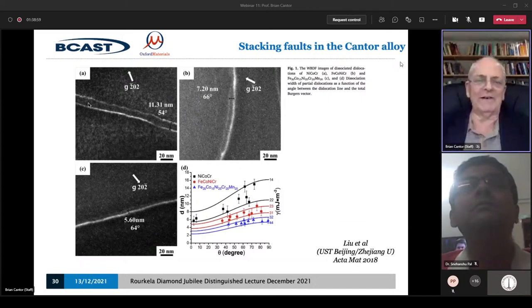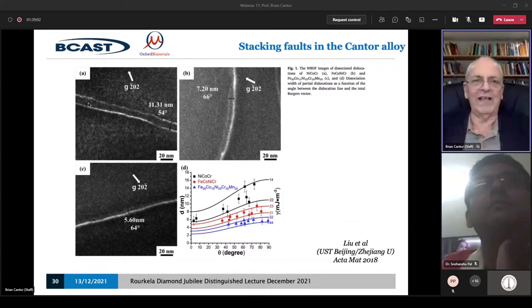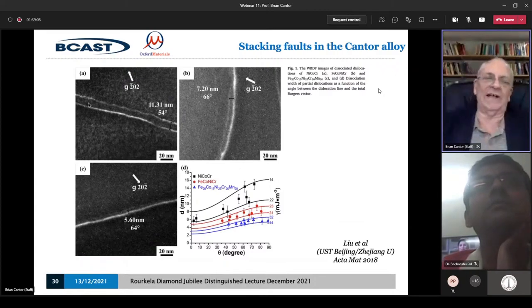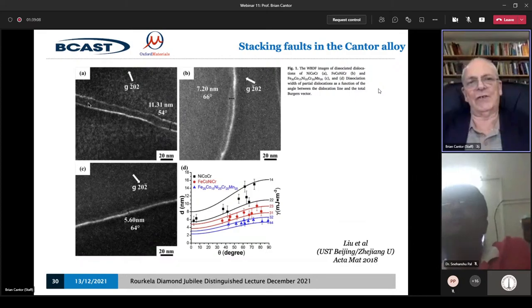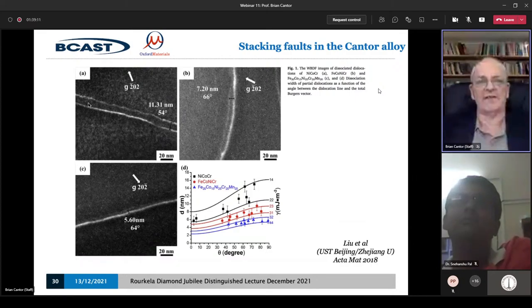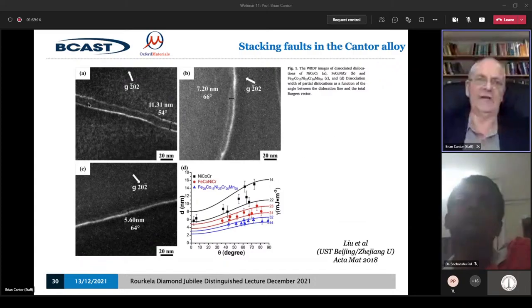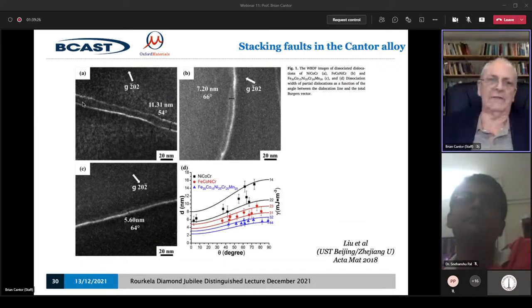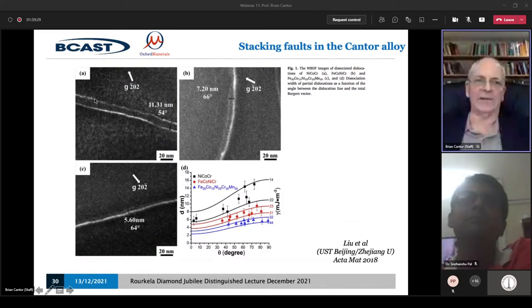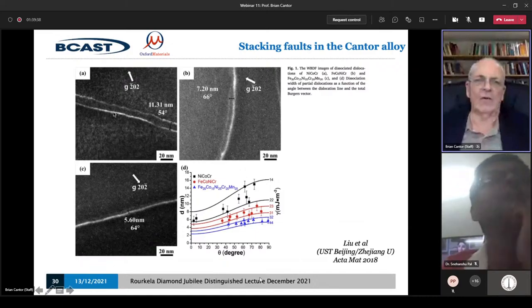For those who are listening and don't know about dislocations, don't worry. There are different kinds of dislocation, and the particular one which is relevant, the one that gives FCC its softness and its fracture resistance, is called a half 110 dislocation, and it moves on a 111 plane. It also separates into partials because of the stacking fault arrangement. The half 110 dislocation turns into 1/6 112 dislocations, and there's a stacking fault separating them.